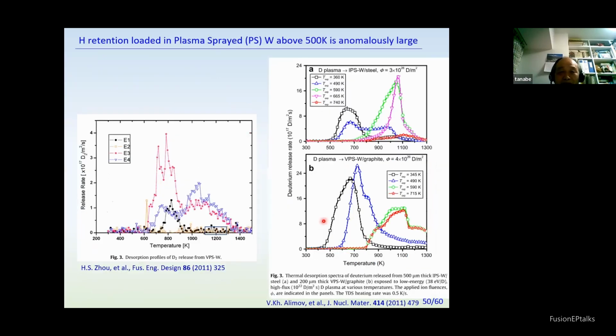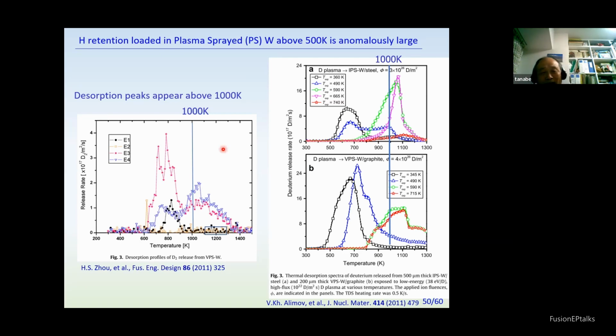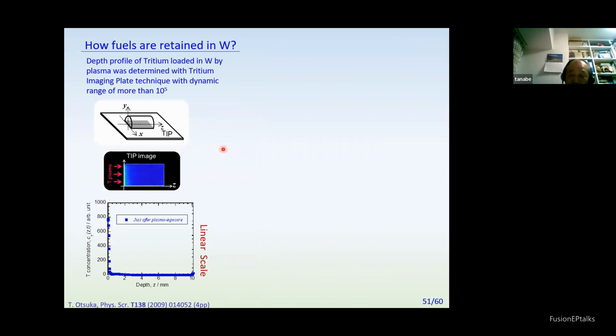And this is significant particularly in plasma sprayed tungsten cases, which give very strong trapping sites - hydrogen implanted VPS tungsten retention appears over 1000 Kelvin. Retention is large, and even at high temperature, tungsten traps the hydrogen. How, in case of tungsten, is hydrogen trapped? Recently, tritium can be used to detect the depth direction of the concentration.